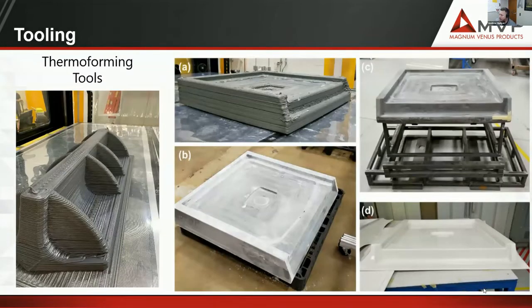In this photo, this is a thermoforming tool that we used. This is one of the first prints that we did. It's probably about 3 feet by 3 feet or 3 feet by 4 feet. We printed the mold and we machined the mold down. And then when it got to the customer, they were able to bond some framework to the mold. They bring an acrylic sheet down, and we had vacuum ports that we drilled underneath, and the acrylic sheet comes down at 300-something degrees, and then we pull the vacuum, and it forms that acrylic sheet on the thermoforming tool to match the tool, and then pops right off. So this tool was in production for a little bit, and how the thermosets stood up to the heat with no issue was pretty amazing.